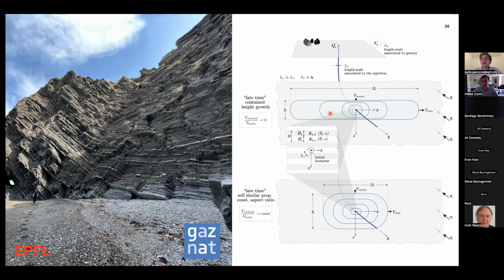So Colin says here, actually it's not an upper bound, because if you're moving into a layer with lower fracture toughness, then the process zone would zoom ahead. So it's not really an upper bound, I don't think. Well, that's a very good point. So you can have nucleation ahead, essentially. Yeah, that's true. We didn't account for that.